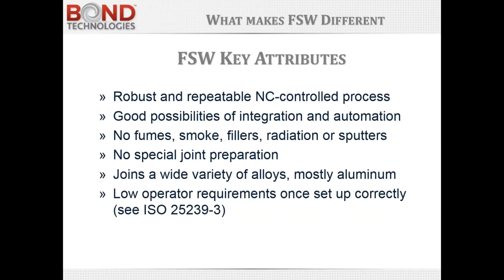Because it uses frictional heat, there are not a lot of fumes or smoke. No filler is used. The only consumable is really the pin tool as it wears over the life of the tool. And I'll say there's no special joint preparation, but I have to caution that the joints do need to be abutted together fairly well so that there aren't large gaps. And in the event of certain welds, oxidation can be an issue, so the removal of oxidation can occasionally be done. But as opposed to melt phase arc welding, for example, the oxides become stirred into the material as opposed to inhibiting the weld process.